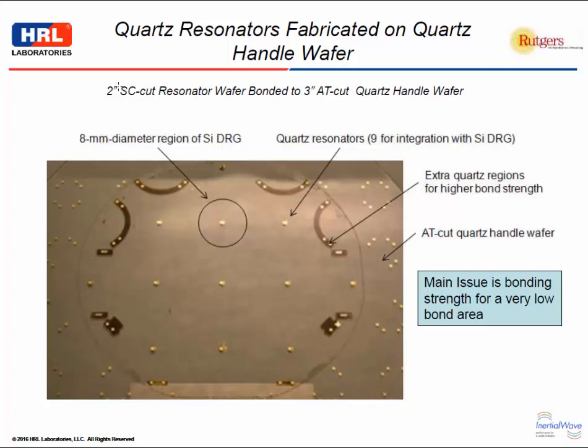And so when we bond this structure to this silicon substrate, there's a very, very low bond area. And we were actually afraid that they just wouldn't hold together, just in handling. So we actually added some extra sacrificial bond areas. These extra little pads here are just for bonding to try to hold things together. We didn't have a problem, as it turned out, so we didn't go back and remove these extra little sacrificial areas. But you can see it's a completely different situation than if you were just processing one type of device.